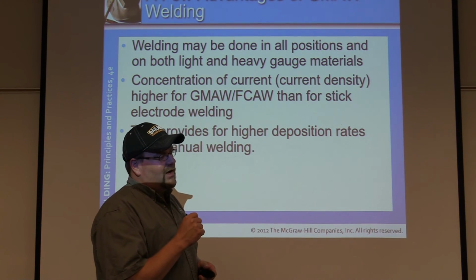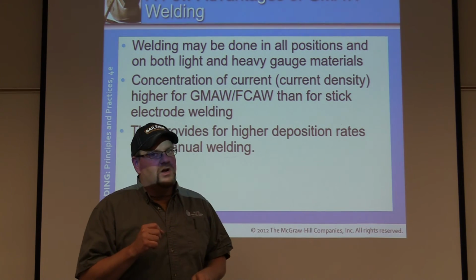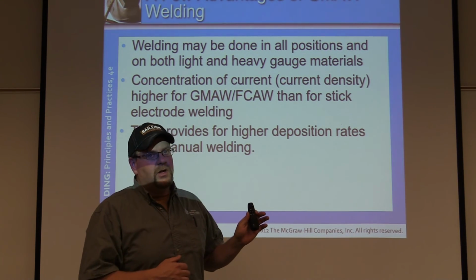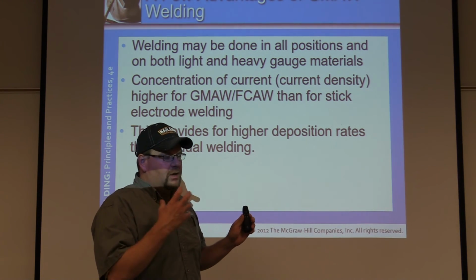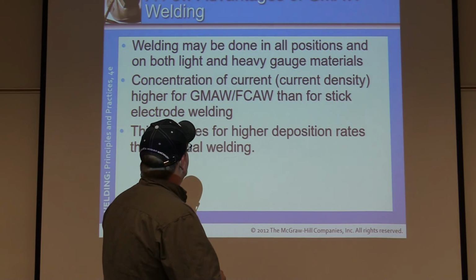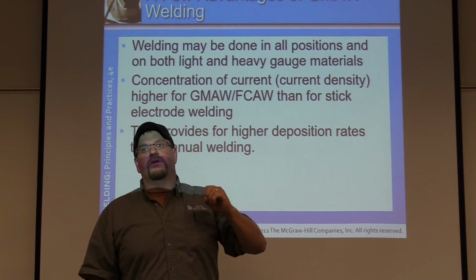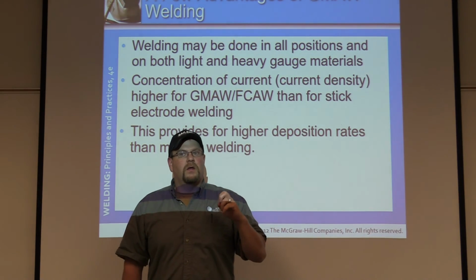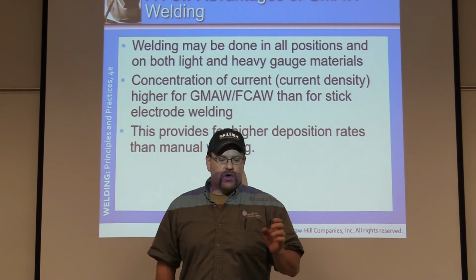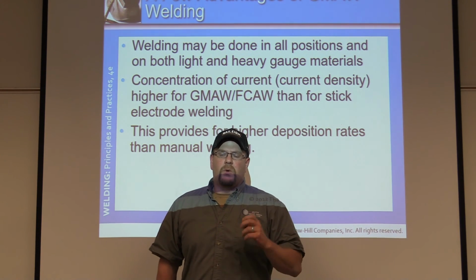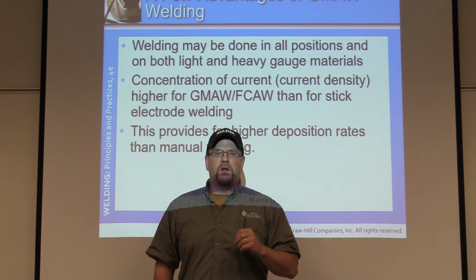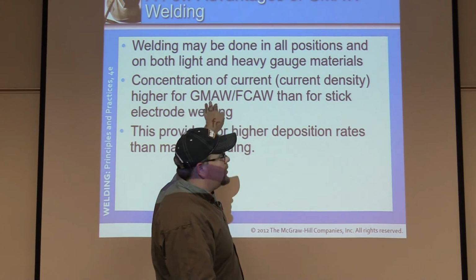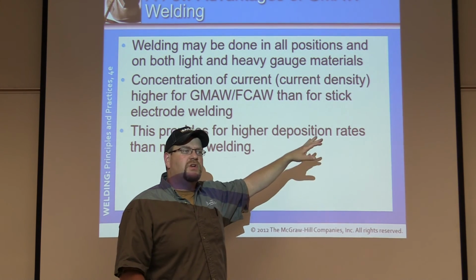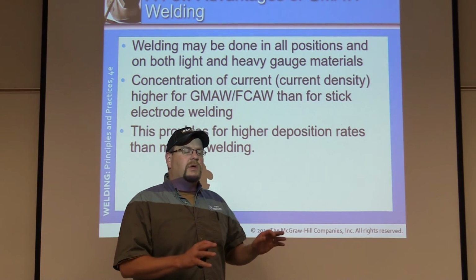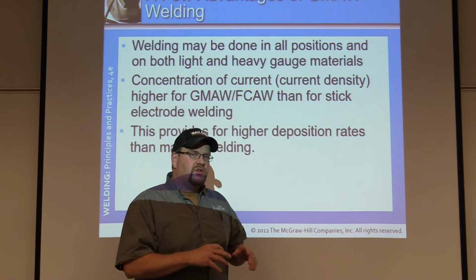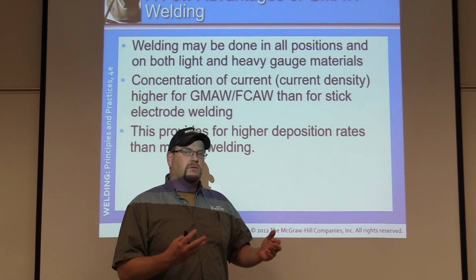However, just because you're seeing a higher concentration of current doesn't mean that your GMAW is hotter than your SMAW. SMAW is still a deeper penetrating welding process, okay? GMAW short circuit transfer is the coldest arc welding process known. So much so that the American Welding Society will not allow any prequalified welding procedures for GMAW short circuit. So every time you want to write a procedure to say this is code quality, it's got to meet a spec, we want to weld it up with GMAW short circuiting transfer, which is what most of us are familiar with in the shop.